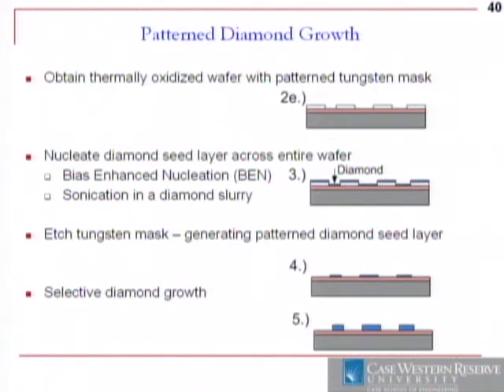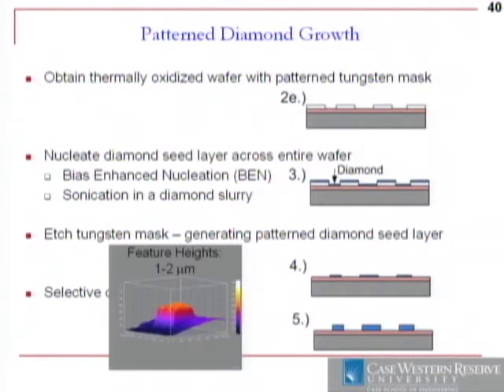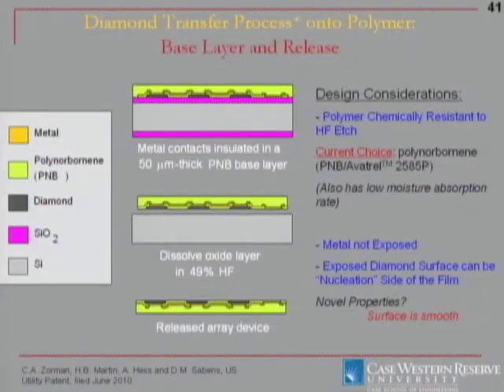We're depositing on silicon dioxide, and we remove the mask and then get selective diamond growth after that to form these pillars, which look something like this under confocal microscopy. So we're actually exposing 3 sides of the diamond that we're going to grab onto with our metal contacts and our polymer support to hopefully make good adhesion to the diamond pads to form our new type of diamond on polymer electrode. And once we have the diamond pattern, then we build up the metal contacts here.